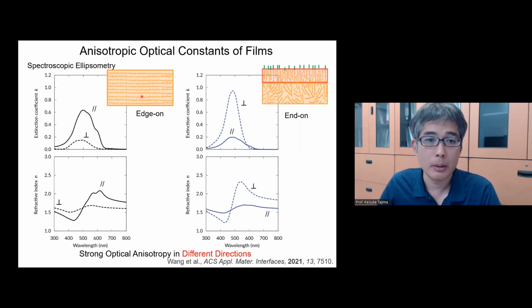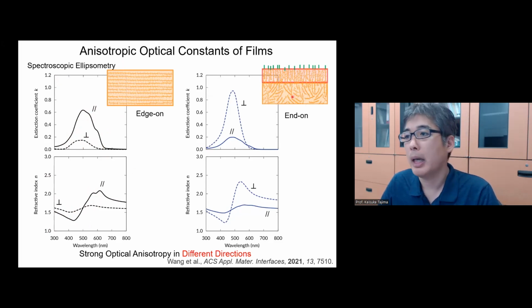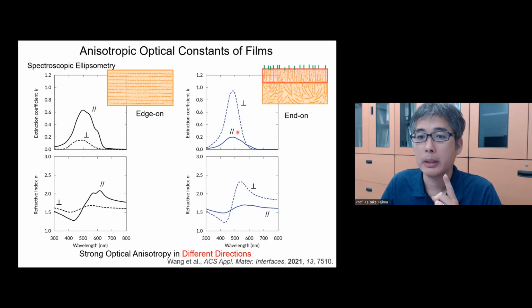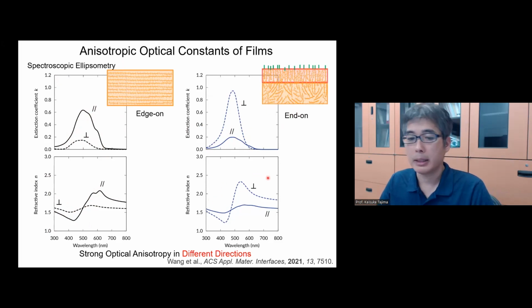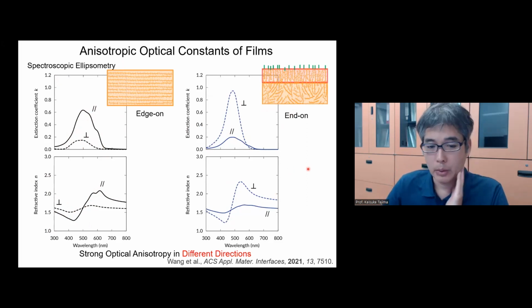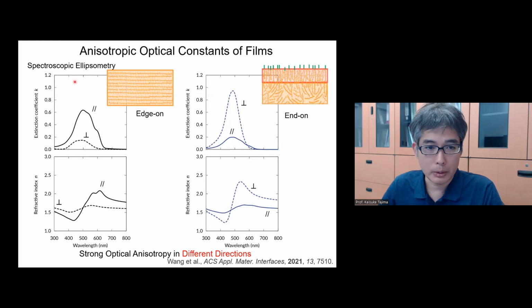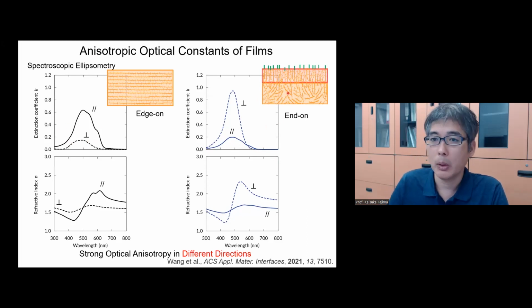One thing is the optical property. Edge-on orientation gives, as I said, better light absorption because the transition dipole moment is aligned in parallel. Using spectroscopic ellipsometry, you can measure the absorption coefficient and the refractive index anisotropy in the film. You can see that in the parallel direction you have a large absorption compared to the vertical direction, similar to the refractive index here. But if you have an end-on orientation, it's completely opposite. In the vertical direction you have a larger absorption than the parallel direction, and the refractive index has the same tendency. So we can achieve a very unique, strong optical anisotropy, whose direction is different from the ordinary case.